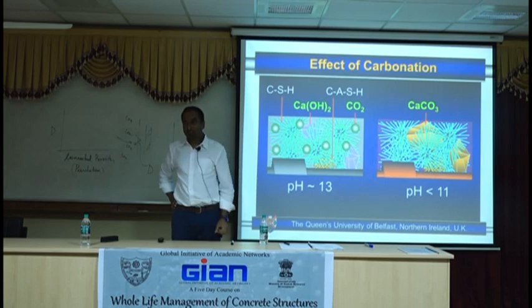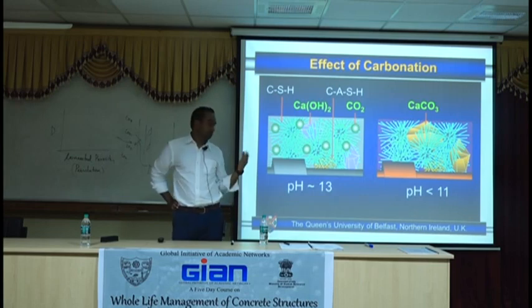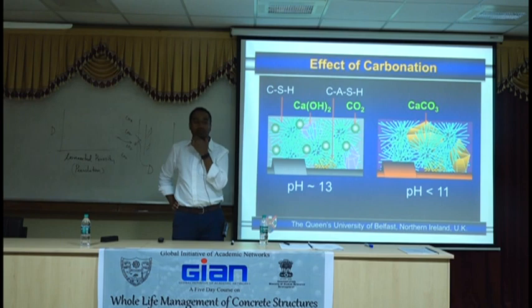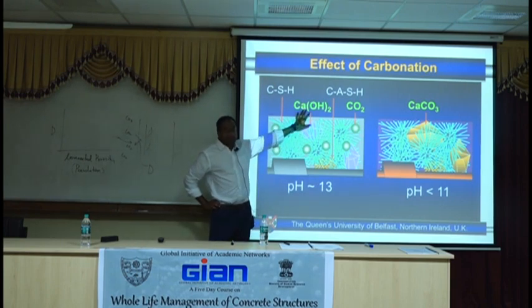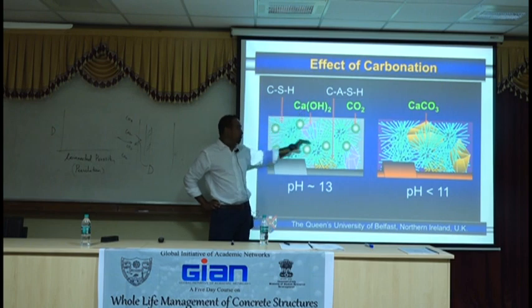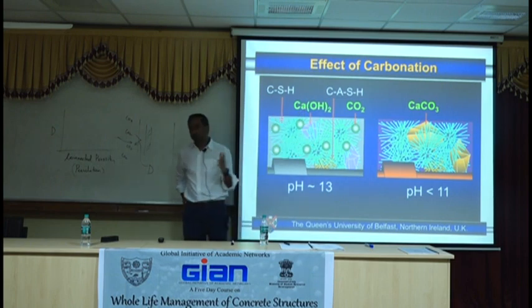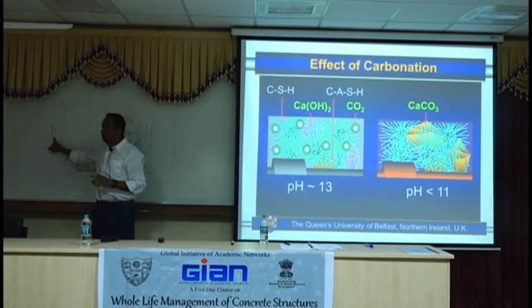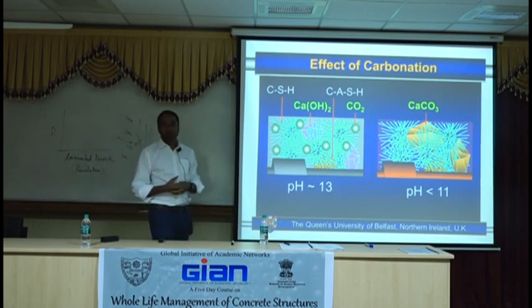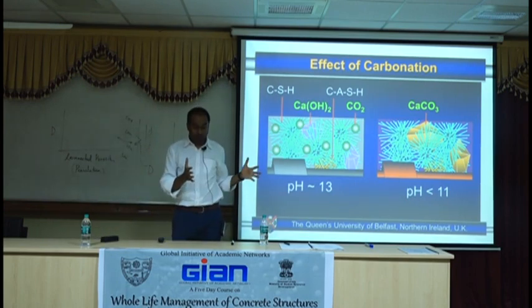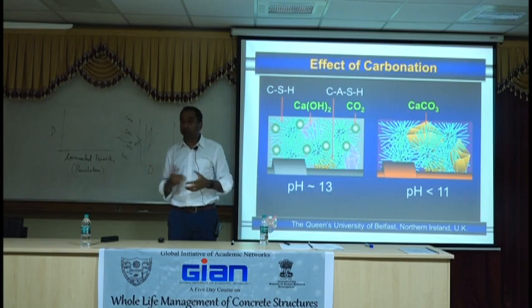free in there. So maybe not for carbonation, but it is a possibility because yes, it takes some calcium hydroxide, but mostly it'll fill the pores. Most of the products are non-reactive. It does reduce the diffusion. It does reduce the flow of CO2, which has a better effect.